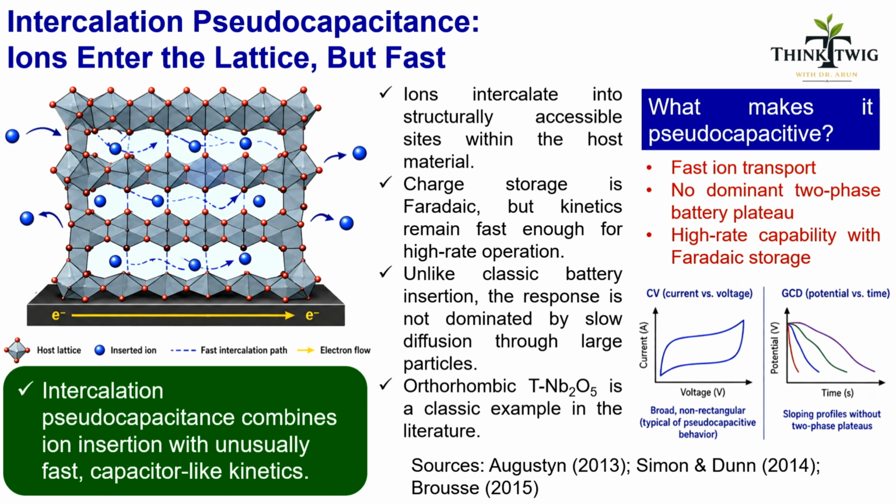And therefore, ion insertion alone does not automatically mean slow battery behavior. The important question is whether the response is dominated by slow, long-range diffusion and major battery-like phase behavior. In intercalation pseudocapacitance, that strong limitation is not dominant. The slide gives orthorhombic Nb2O5 as a classic literature example.